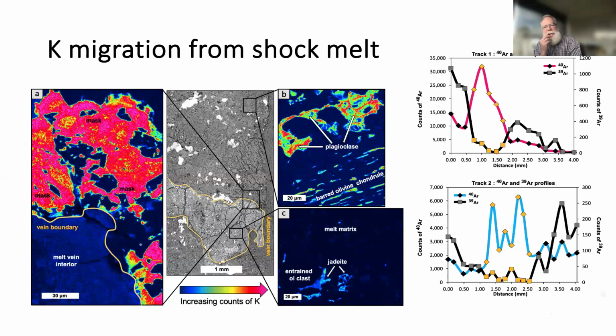This is a potassium map. This is an EDS map, potassium map. And what you see is the melt vein interior has very little potassium, and the maskelynite outside the melt vein is loaded with potassium. Here is maskelynite or plagioclase far from the melt vein. It has significant potassium too, but much less than the stuff that's neighboring the shock vein. Here is a little bit of residual plagioclase. What was plagioclase in the melt vein is now a jadeite assemblage, and it has some potassium in it. But basically, the melt vein is virtually devoid of potassium.